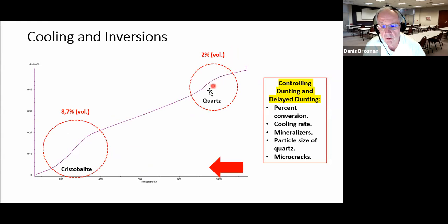we have to cool more slowly through the quartz area. So that's another reason that ceramics firing schedules can be adjusted to be very slow cooling through quartz, because that quartz inversion can cause cracking. And if cracks link up, then your product can fracture more readily, either in the kiln or later on. So if you want to meet your strength standards, you're probably going to cool in a controlled manner through the quartz inversion.